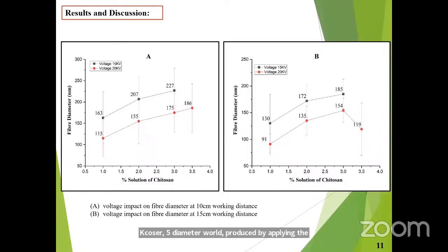In general, long working distance promotes higher draft in the polymer jet during electrospinning. However, bending instability of the jet in the presence of an electric field is also very important in this phenomenon. Therefore, longer working distance accounts for higher whipping instability of the jet and is responsible for the reduction of diameter of the resultant fiber due to acceleration and higher stretching before the fiber deposition on the collector. As a result, fiber diameter reduces with the increase of working distance.